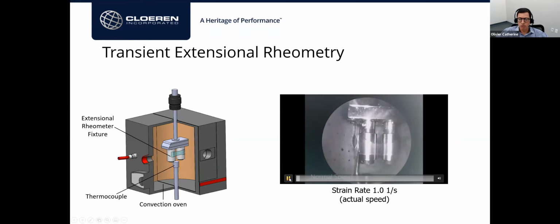For example, here, a tool I really like is being able to measure transient extensional rheology. And the way it works, we basically use a piece of film of a given sample and melt it in a convection oven, and then we start stretching it with those rotating drums. I have here a little movie. Unfortunately, my camera, which I really liked, got flooded during one of our hurricanes here in Texas, and so I lost that camera and that capability. But you can see, it was really cool.